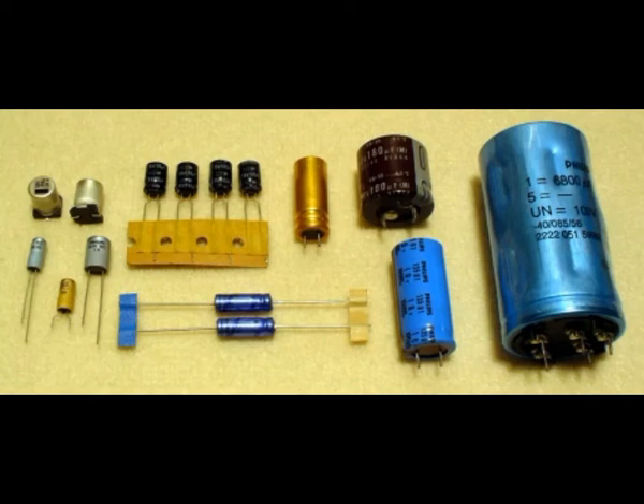The ability of non-solid aluminum electrolytic capacitors to have a stable behavior during longer storage times can be tested by using an accelerating test of storing the capacitors at their upper category temperature for a certain period, usually 1000 hours, without voltage applied. This shelf life test is a good indicator for an inert chemical behavior of the electrolytic system against the dielectric aluminum oxide layer, because all chemical reactions are accelerated by high temperatures. Nearly all of today's series of capacitors fulfill the 1000 hours shelf life test, which is equivalent to a minimum of 5 years of storage at room temperature.